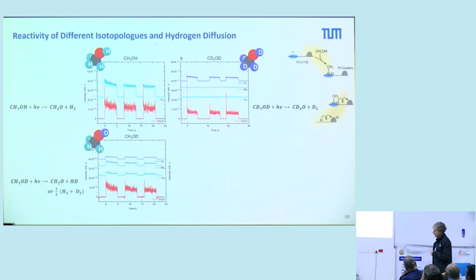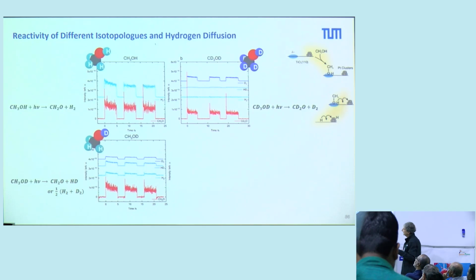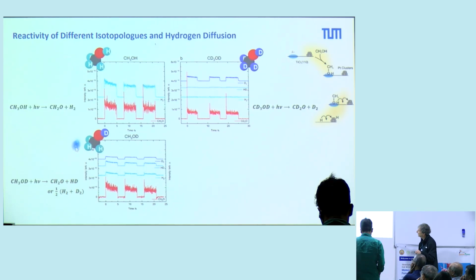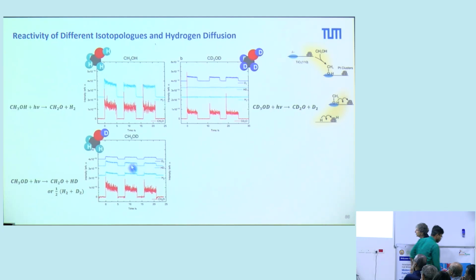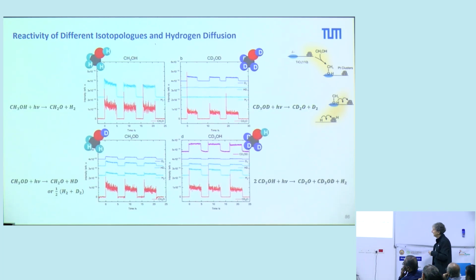And you can also use other isotopologues, CH3OD. And here you see that you have a statistical formation of D2, H2, and HD. That means you have the same concentration of these species at steady state around the cluster because you have this statistical distribution.